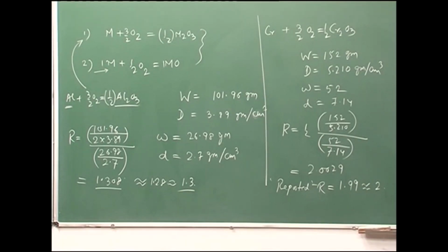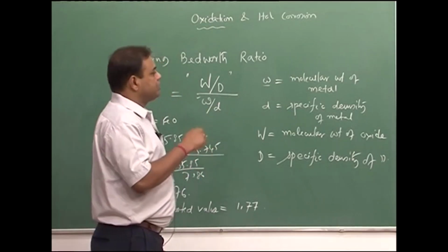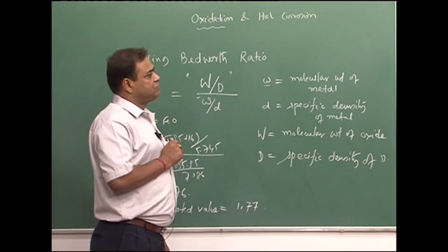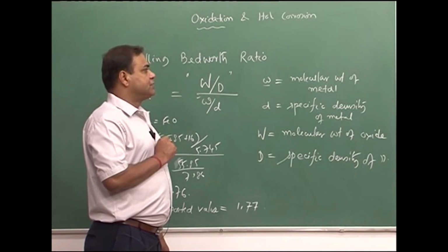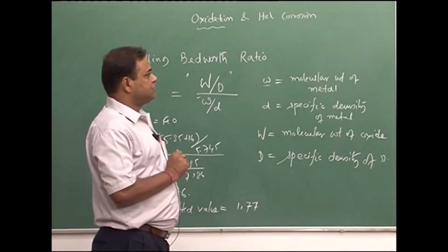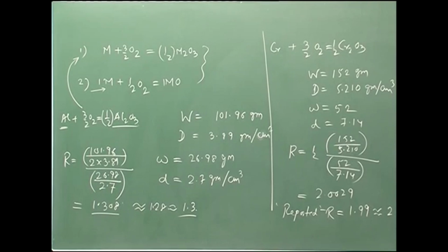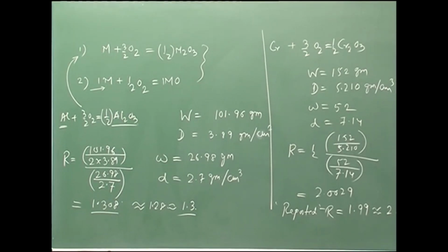And if it is less, it is not going to cover up the entire surface. So, we can have some exposed area of the metal where oxidation can take place, but if it can cover up the entire surface, then we can have a good resistance, which is expected, provided that the metal oxide is not evaporating type.